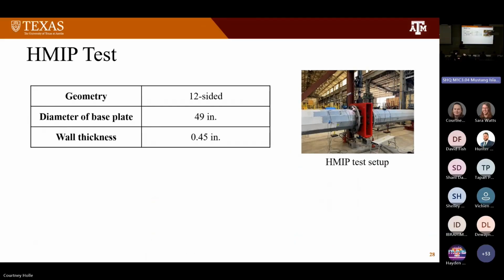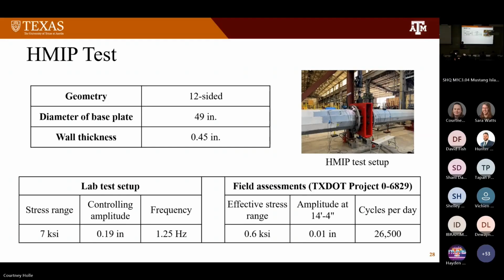We used a 12-sided HMIP specimen. The diameter of the base plate is about 49 inches, and the wall thickness is about 0.45 inches. In the lab test setup, we applied a stress range of 7 KSI with a controlling amplitude of 0.19 inches at a loading frequency of 1.25 hertz. For comparison, field data of an in-service HMIP in Austin shows an effective stress range of only 0.6 KSI, amplitude of 0.01 inches at the same height, and 26.5 thousand cycles per day.